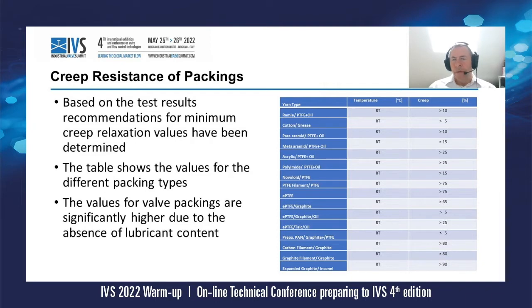You see the difference here in the creep values for the typical pump packings which contain grease or lubricant as the running-in lubricant. These values are quite low because again the oil will run out under pressure, which is intended for pump packings to counteract the heat dissipation.